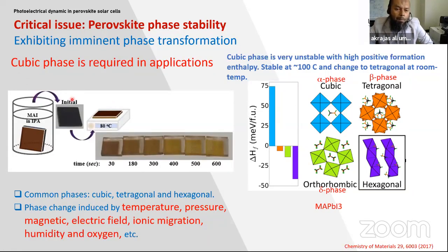For the cubic phase, the color of the film is black at around 100 degrees Celsius, and it changes to yellow, which is the tetragonal phase, which is much more stable with low enthalpy. It becomes yellow at room temperature. Thus, this is not photoactive anymore. So actually, this is our task for those who are interested in the field. Our aim is to soon find a suitable approach to control the stability of the device or the material, so we can realize high performance optoelectronic devices in real applications.